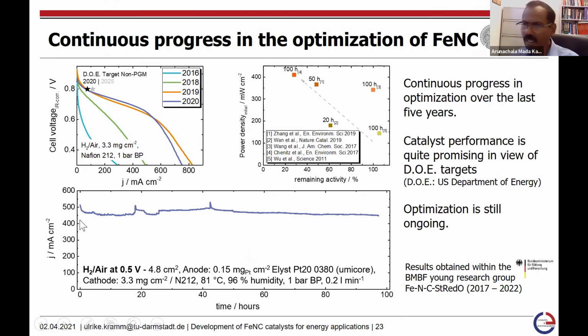And this kind of stability is probably not meeting the DOE requirement in terms of stability, right? So for the DOE, stability is defined by cycling. We did not perform cycling, but potentiostatic measurements. Still, in the literature, most of the work that you find is potentiostatic, and based on that, we selected this condition to have a better comparison to literature.